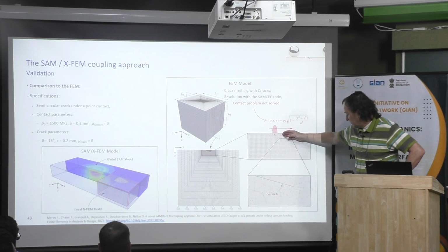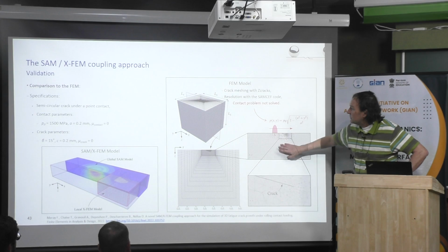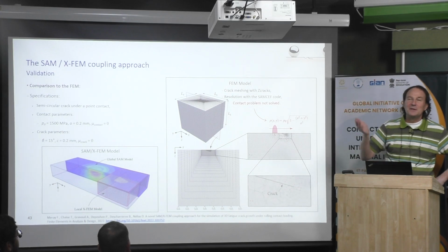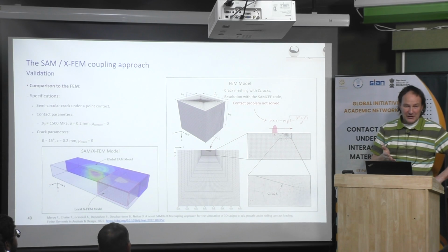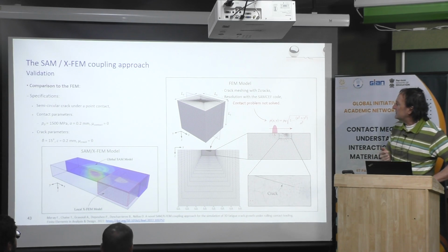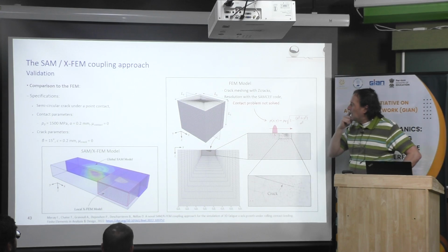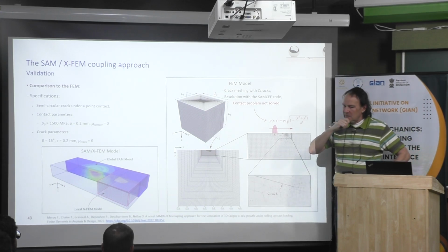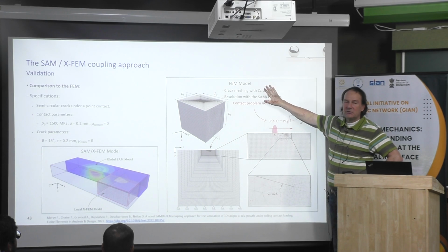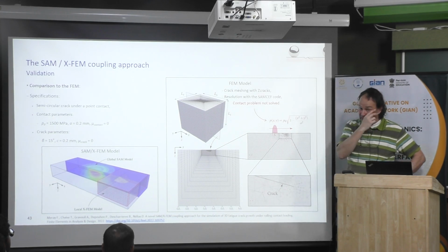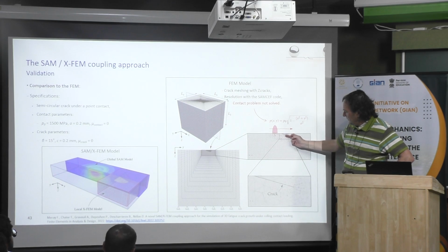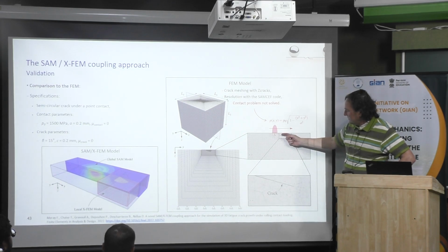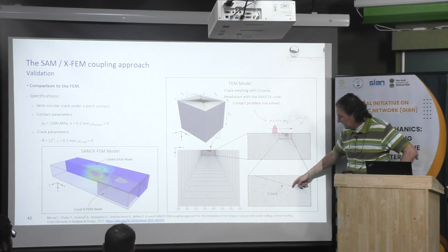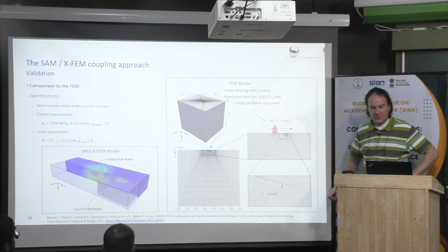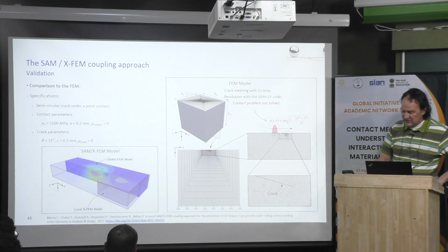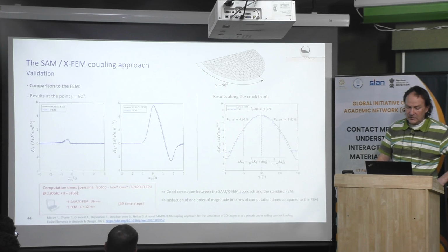Okay, then you can see here the crack. Then, okay, first we did, because we are working for a company, they wanted to have a comparison to their model, and they have a model which is based on Zcracks with the SAMCEF. Okay, this is something done by another group in Paris, in France. Here, they study the propagation of the crack each time by remeshing the crack after each time step. Okay, but this way we found the same results, and that validated our tool.